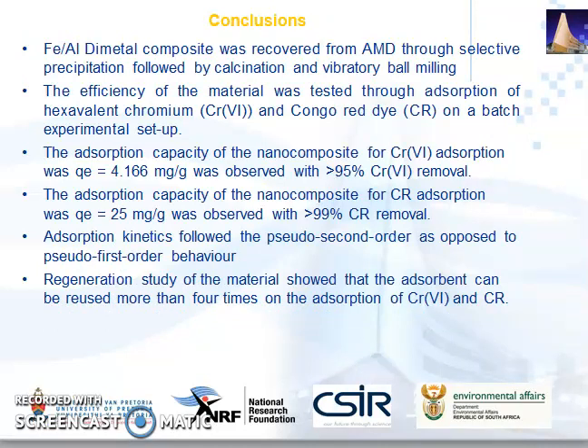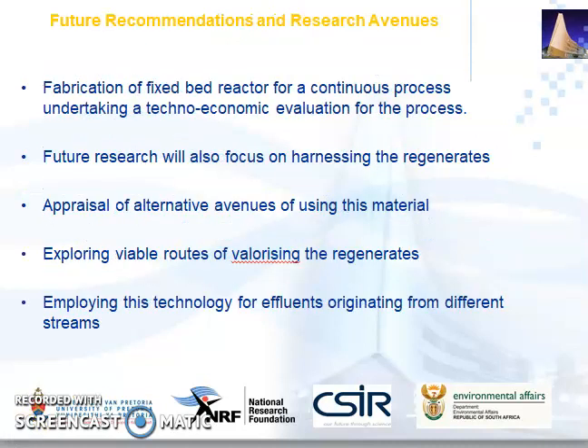Iron-aluminum di-metal composite was successfully recovered and synthesized from acid mine drainage through selective precipitation, and its efficiency was tested through adsorption of hexavalent chromium and Congo red dye in a batch experimental approach. The material successfully removed more than 95% of chromium-6 and more than 99% of Congo red dye from wastewater at optimized conditions. A regeneration study showed that the material can be efficiently used more than four times. Future recommendations include the fabrication of a fixed bed reactor for a continuous process, research focusing on harnessing the regenerates, and exploring viable options for valorizing the regenerates.